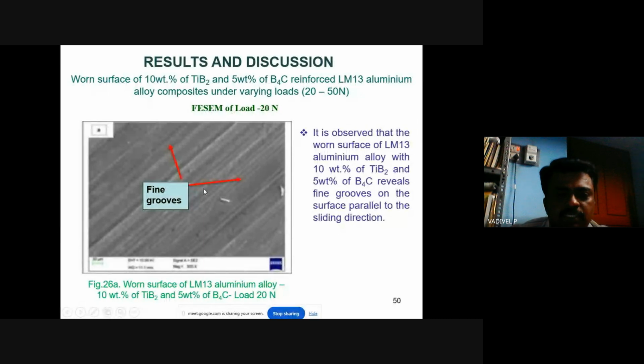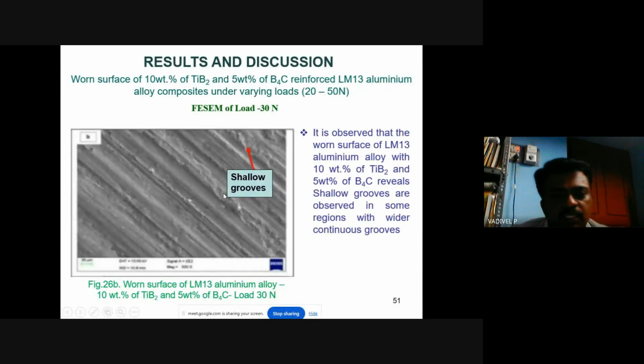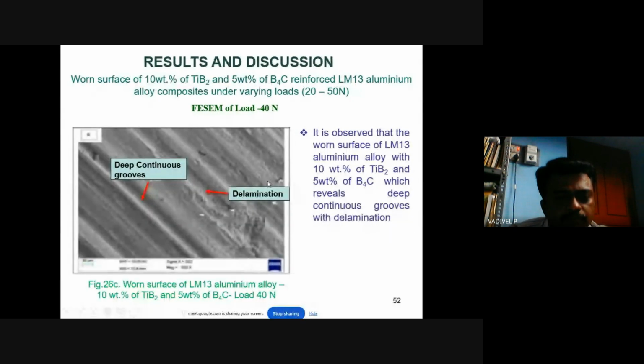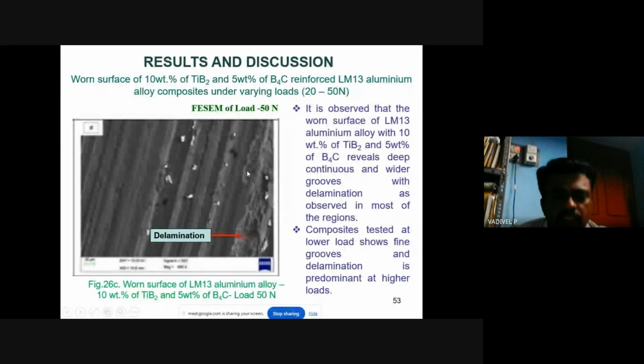And with the load test, this is the FESEM image with 20 Newton of load applied on the specimen. And the next one is 30 Newton load applied on the wear test apparatus, so that we obtain shallow grooves. When we apply 40 Newton of load, we observed deep continuous grooves, and delamination is also noted here. With the load of 50 Newton in this test, the delamination is maximum. It reveals deep grooves, and delamination is also observed in most of the regions. The composite tested at a lower load shows fine grooves, and delamination is predominant at higher loads.